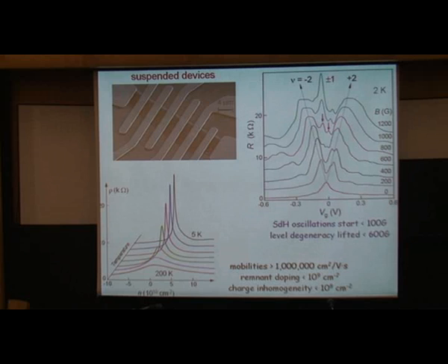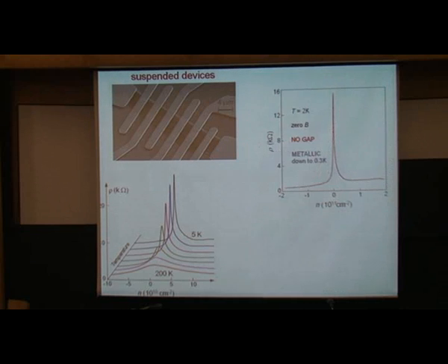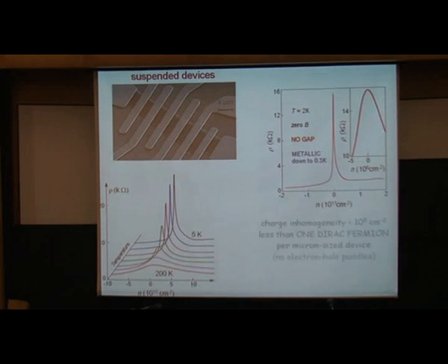So, how to explain it in simpler terms? If you apply a magnetic field, you start seeing quantum oscillations at essentially 100 Gauss. Not quite the Earth's magnetic field, but close to that, and you lift all degeneracy of all the levels in the field of a weak permanent magnet, essentially. So quantization is an extremely strong phenomenon. Particularly, I like the fact how sharp those peaks are. At high temperatures, there is thermal broadening. At low temperatures, the peaks are extremely high. And if you translate this broadening in terms of the number of electrons per typical device, you get around one electron or one hole or one combined particle, which I'll explain later, called a Dirac fermion, in those devices. There is no inhomogeneity left in this device.